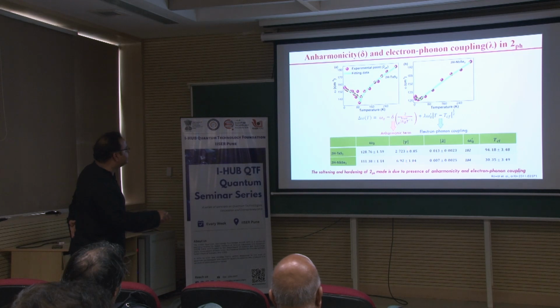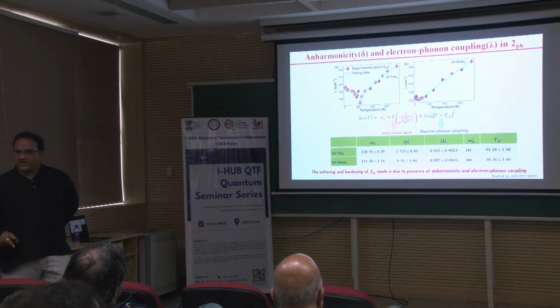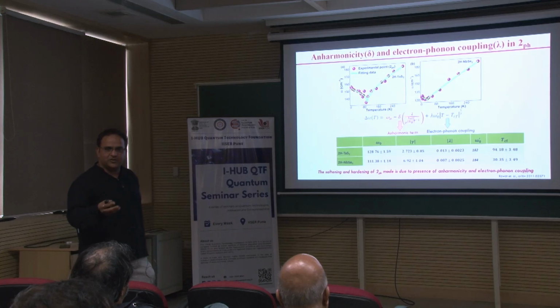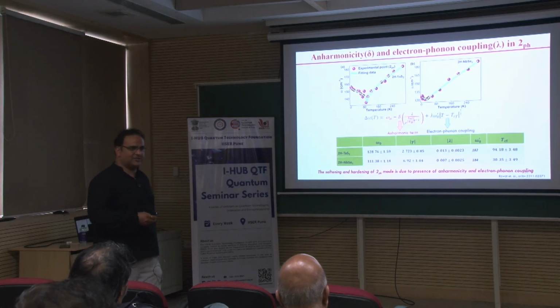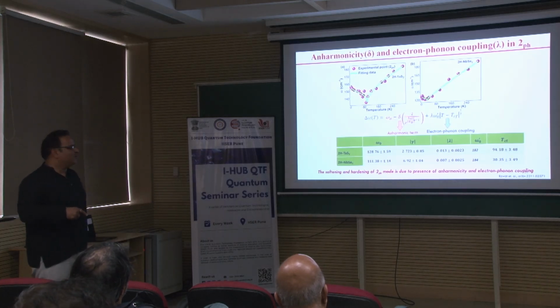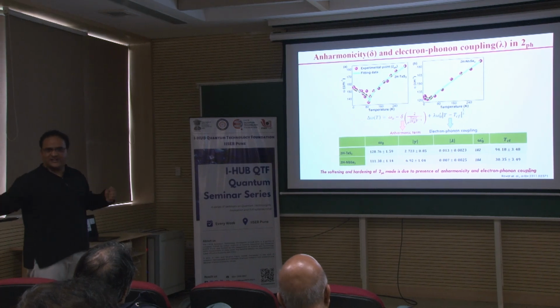Lambda is here. So, you see the niobium selenide is more anharmonic, while the electron phonon coupling is higher in tantalum sulphide. And now we wanted to probe more into the electron phonon coupling, because that is the signature we get. That is why we chose tantalum sulphide over niobium selenide to exfoliate it and see what is the